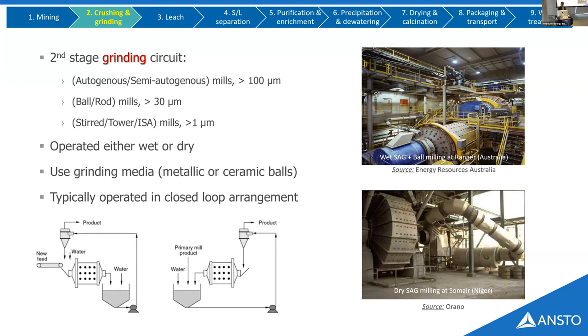Okay. The photo at the top there, when Ranger was operating, actually had a combination of wet semi-autogenous milling and ball milling to get the liberation. In Niger, Somaïr actually uses dry SAG milling. Somaïr is in the Sahara Desert, so you would think that dry milling is for water conservation purposes. Do you agree? That was my belief first as well when I started, but it's not. There's lots of water underneath in the aquifers, but the dry milling is used because down the process, when you're getting the uranium out, you can have about 5 to 8% more recovery. It's just the fact that minerals respond better with the heat and in a dry space.